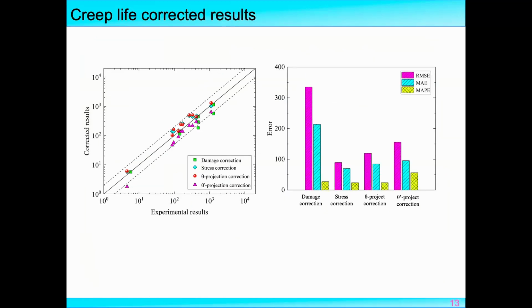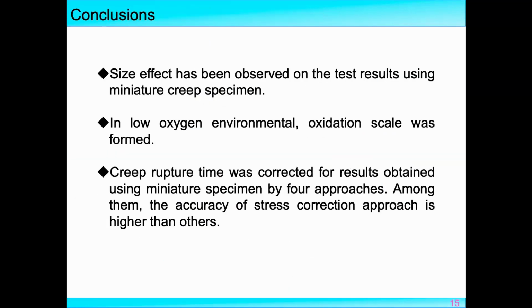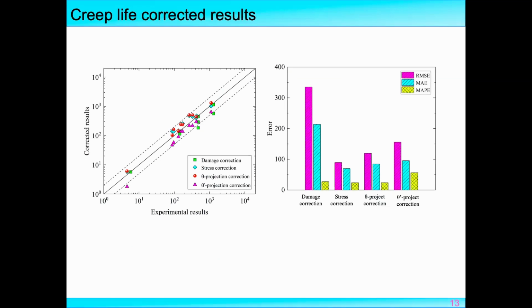And here is the corrected result. From this figure, we can see that almost all corrected results are distributed within the plus-minus 2 factor line. However, when we quantitatively analyze the error for the 4 methods using the following 3 standards, RMSE, MAE, and MAPE, we can see that the damage correction and the theta prime projection are not so good. And for the stress correction method and the theta projection method, the RMSE of the theta projection method is slightly higher than the stress correction method. However, the other 2 standards, MAE and MAPE, are almost the same.